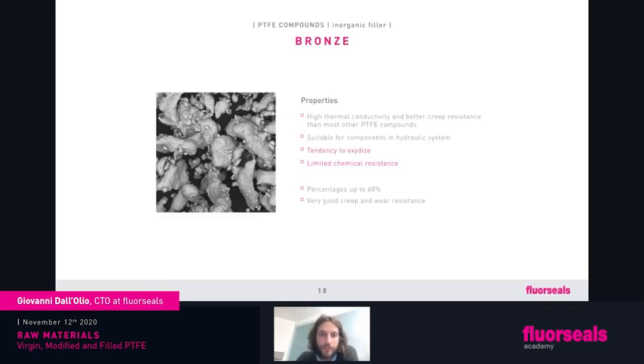Last but not the least is the bronze filler. Bronze is, I guess, probably the best filler for PTFE, but has one problem: the limited chemical resistance. We know that PTFE is widely used thanks to its chemical resistance. So when we add bronze and the chemical resistance is reduced, we cannot use bronze compound everywhere. But the properties are, I would say, the best. We do have the best deformation under load thanks to the bronze filler. The wear behavior is incredible. And this compound can reach up to 60% of filler, mainly in piston seals, for hydraulic pistons. Bronze is the go-to material. Of course, we have the problem of the chemical resistance.